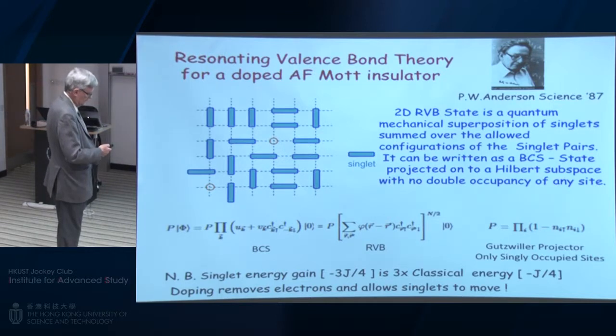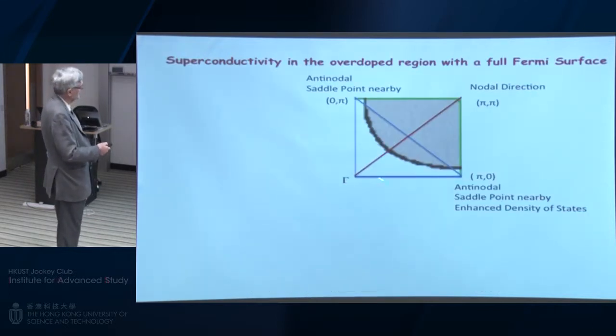But this theory is a beautiful idea, but it has turned out to be hard to work out in practice. So let me look at the superconductivity in the cuprates from the other side, namely when we have a lot of holes, and there we have a more conventional full Fermi surface measured in the experiment. And let me point out that this Fermi surface is anisotropic in K-space, because in this band structure, this is just a quarter of the zone I've shown, these points where it approaches the edge of the Brillouin zone, there is a saddle point. And in 2 dimensions, that gives rise to a Van Hove singularity. And so we have a great enhancement of the density of states in this part of K-space. So we have something that is not isotropic in K-space, but enhanced.